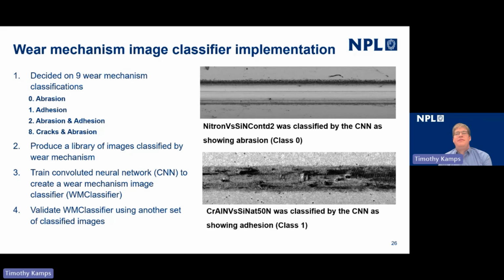We actually produced a very large data set, over 10,000 images, and the images were classified by a number of scientists into 9 different wear mechanism classifications. In this presentation, I'll just look at 4 classifications: abrasion, adhesion, abrasion and adhesion, cracks, and abrasion. On the right-hand side, you can see an example of abrasion, class 0. This was for silicon nitride coating. And at the bottom, we can see a chromium aluminium nitride coating.